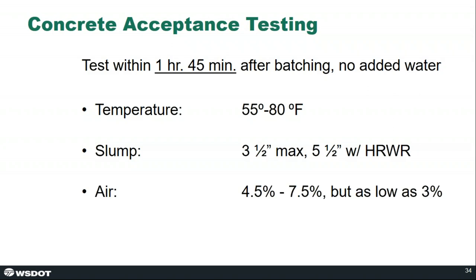And we also measure for air prior to placement. So again, 4.5 to 7.5%, but we allow them to go as low as a 3% air content if they perform the freeze-thaw testing to demonstrate adequate durability.